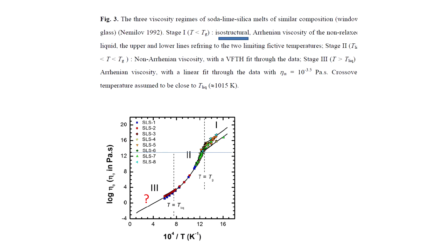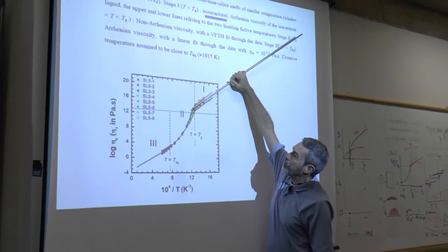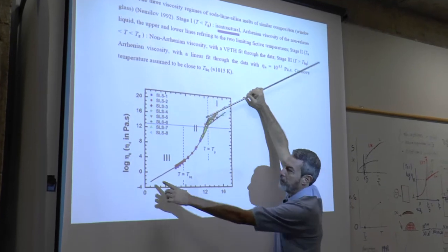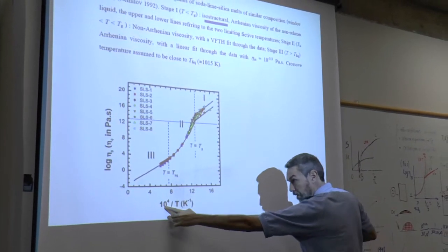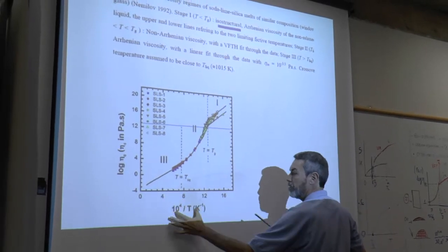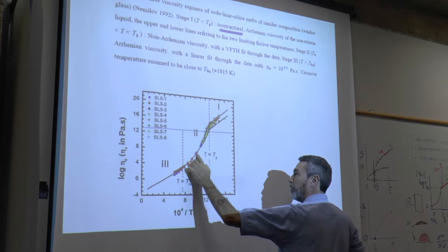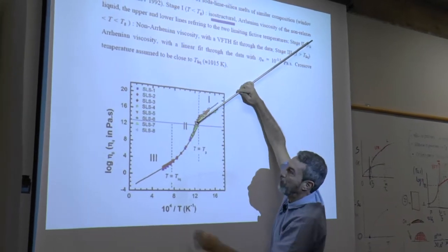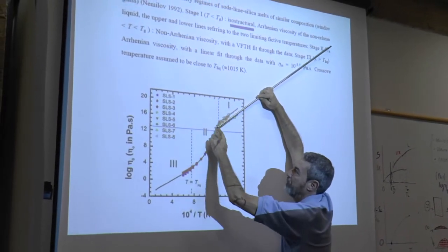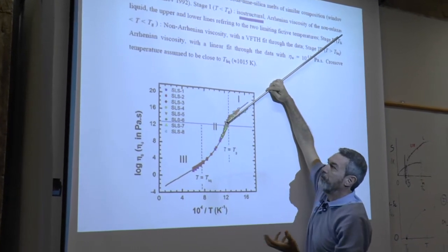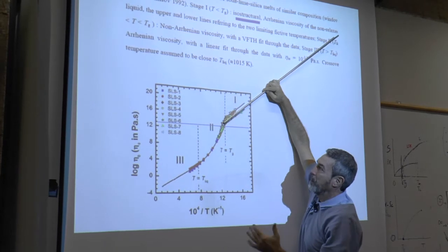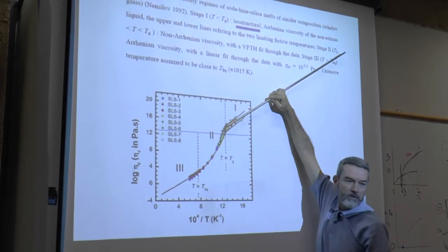Now, one key feature we are going to discuss today, because it's important for relaxation, is this isostructural viscosity. The log viscosity versus inverse of temperature. Even in this inverse of temperature scale it is a curve, not Arrhenian, but then becomes Arrhenian below Tg. This is more or less the Tg. This is when the structure freezes, more or less. And then we have isostructural viscosities.